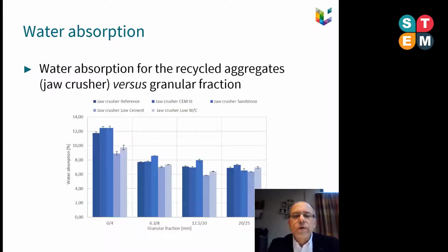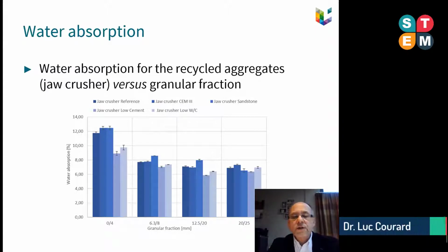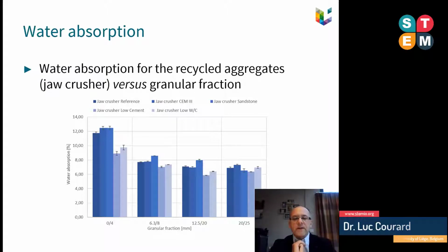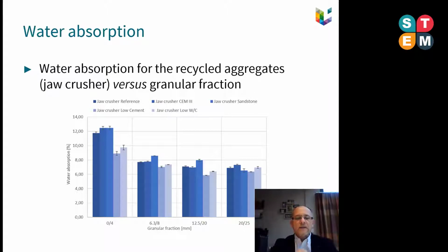We observe also that the water absorption, which corresponds to the quantity of residual cement paste adhering to the former aggregates, is also higher for a lower granular fraction. That means that in sand particles we have a larger quantity of residual cementitious material, which is detrimental, of course, for the characteristics of the material to be recycled.